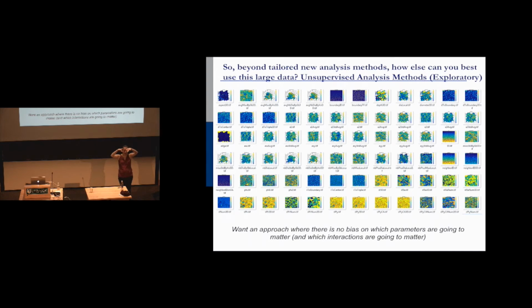And you basically run through different weightings to try to make your microstructural clusters match where damage is inducing. Not point by point, but like, 80% of the time, when I have a really big grain, and I have a lot of misorientation, and I have a small grain next to it, then I get this. So it's looking at these types of interactions between variables too. We're doing an approach that tries to not just look at one variable like grain size, but we're using hierarchical principal component analysis to look at interactions between variables.